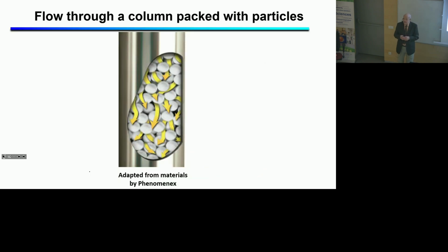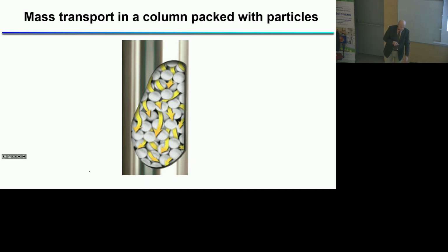Let's have a look at such a packed column. So this is an example of how this packed column looks like. We have these porous particles right here, and the liquids that we are pumping through this column go through the interstitial spaces between the particles. Typically, the rule is that essentially the size of these intraparticle voids is about 20% of the size of the particle itself. So if you have 10 micron particles, this is about a 2 micrometer space. Now, I spoke already a little bit about the mass transfer.